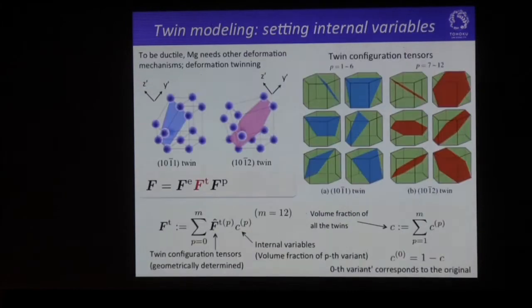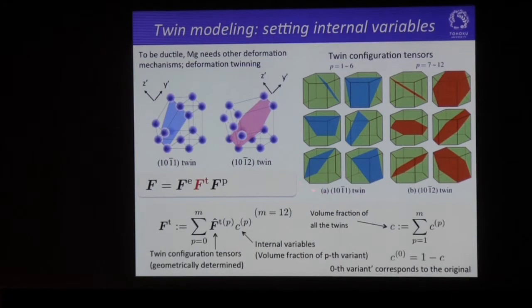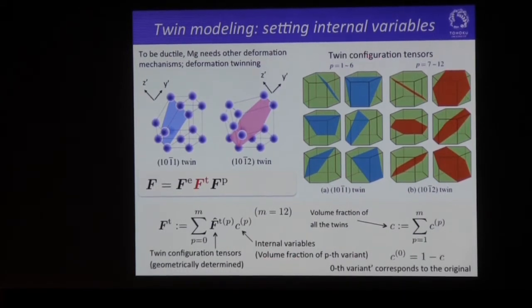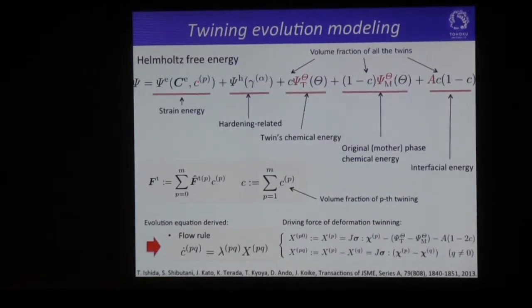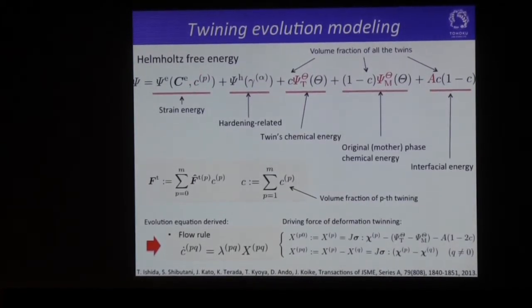Okay, can you see? Oops. Here. So I have already introduced the twinning deformation gradient here. So we assume the twinning deformation gradient of this form. Here is the twin configuration tensor that can be determined geometrically. And some of them are depicted in this figure here. And also this variable is the internal variable that represents the volume fraction of the variant of the twin deformation gradient here. So we introduce this free energy that contains the internal variable here.